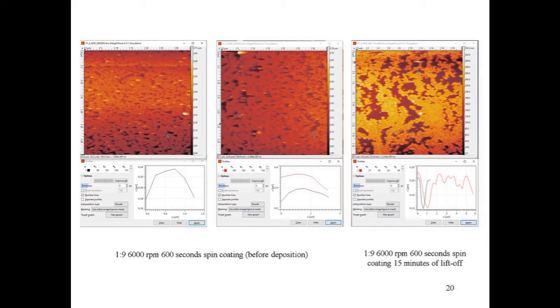Another sample at the same parameters was lifted off for 15 minutes. We understood that 200 nanometer polystyrene nanospheres were not appropriate for our experiment. So we decided to increase the diameter of the nanospheres and change our coating method to dip coating.